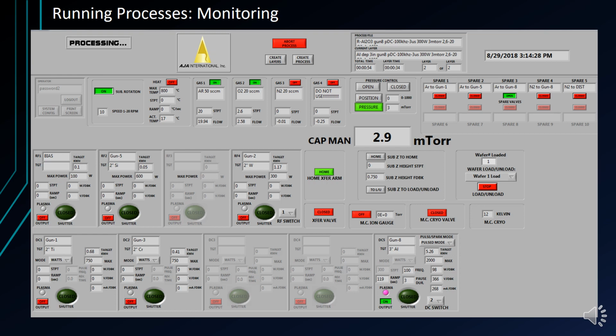Looking at the power supplies, DC5 is connected to switch position 2, which is at gun 8 and holding a 3-inch aluminum target. The power supply is operating in constant power mode and is set to pulse mode with a 100 kHz frequency and a 3 microsecond pause duration. The shutter is currently closed.